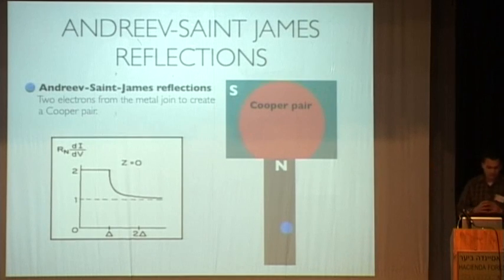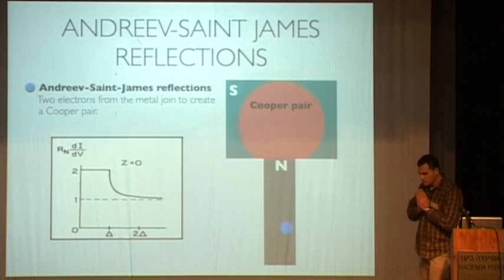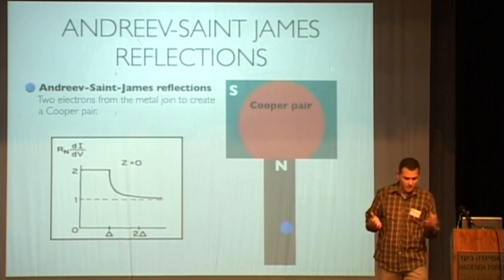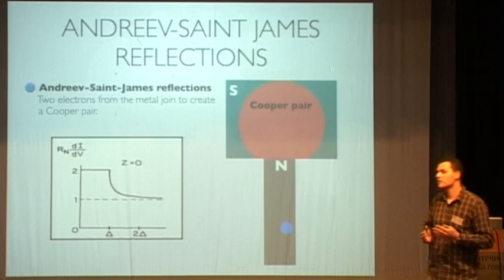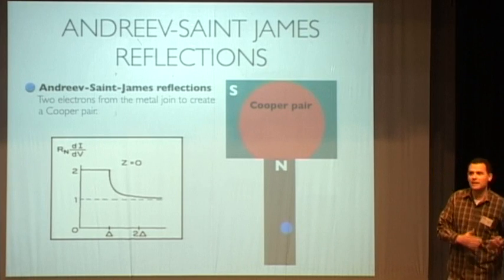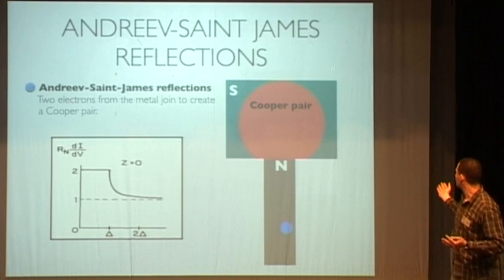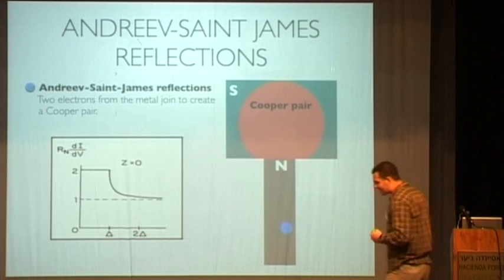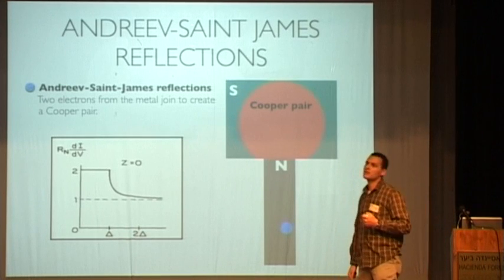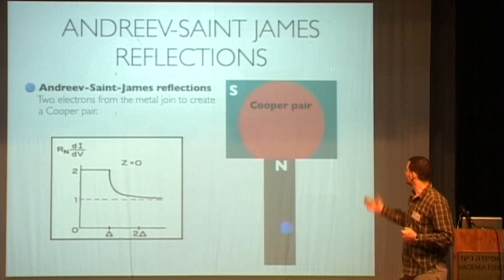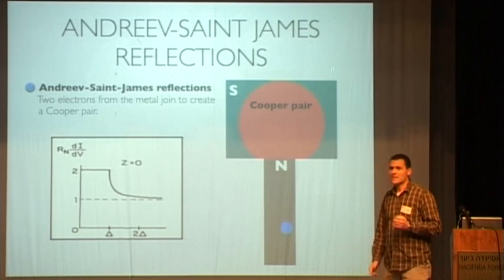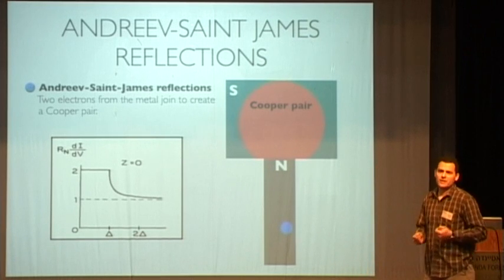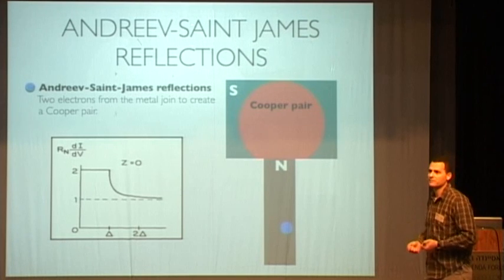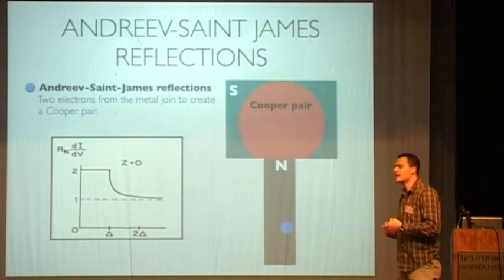And the tool that we use is transport measurement. We measure the current that flows between a normal metal, or a ferromagnetic metal for that matter, and a superconductor. And the basic mechanism for transport of current into the superconductor is called Andreev reflection. And basically what it means is that an electron cannot enter by itself into the superconductor. It has to combine with another electron.